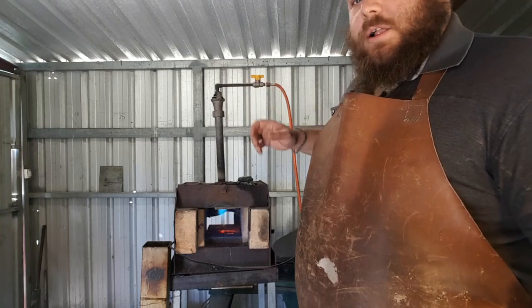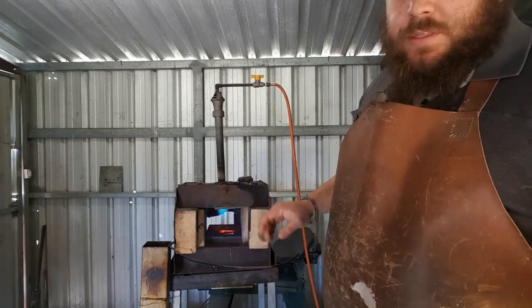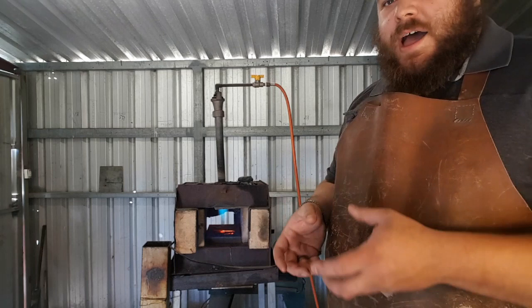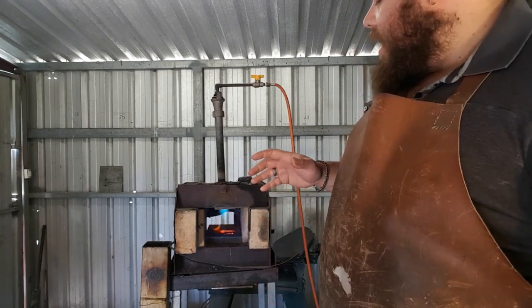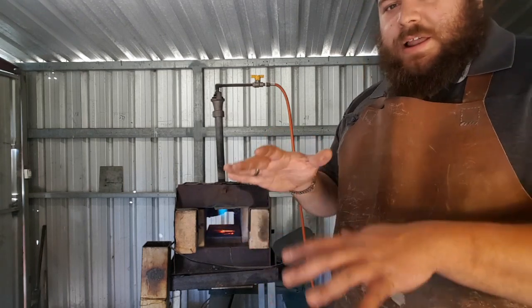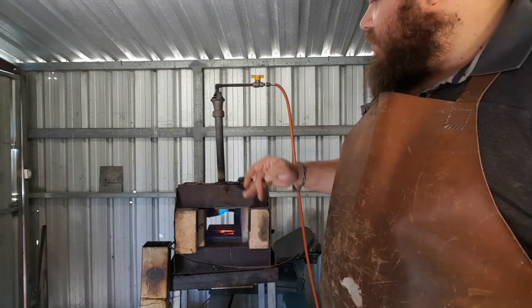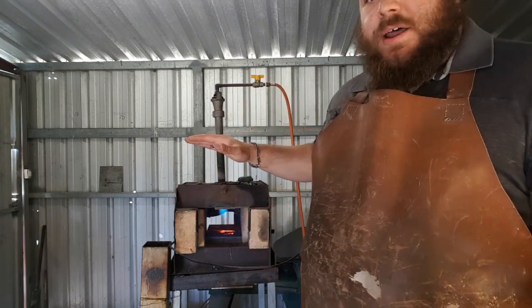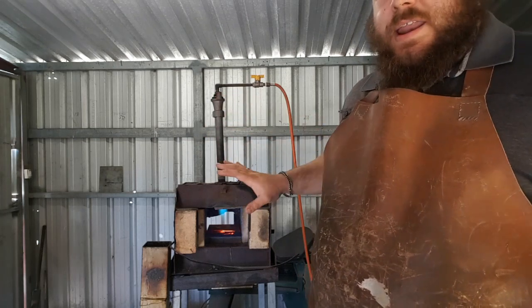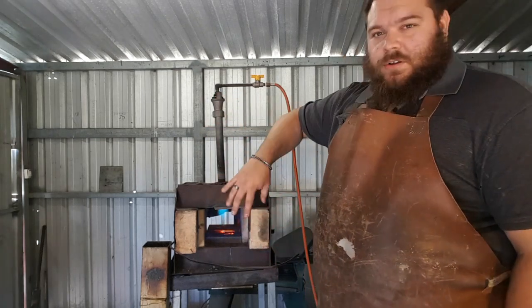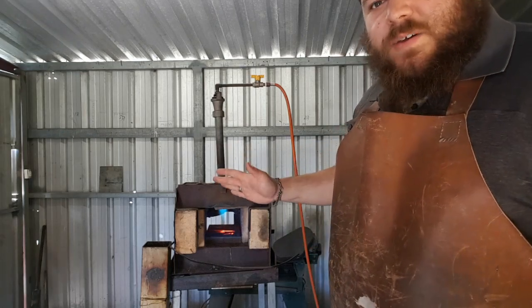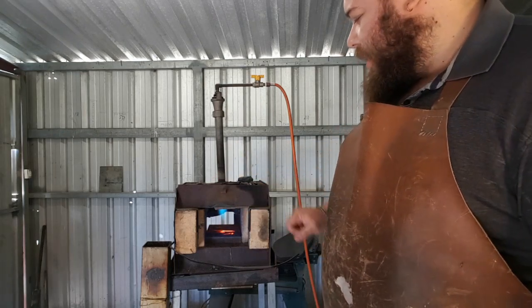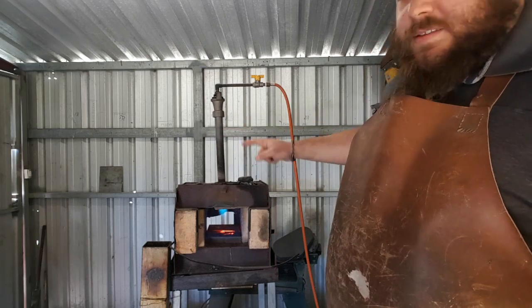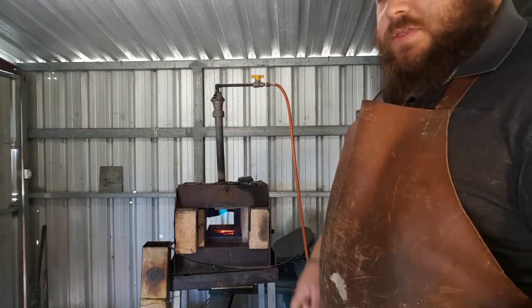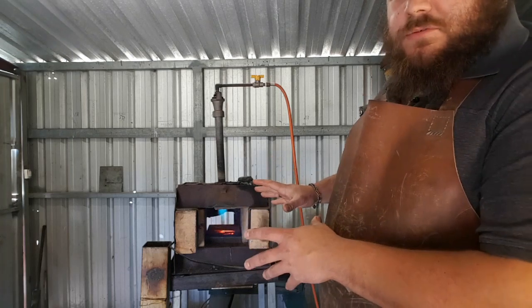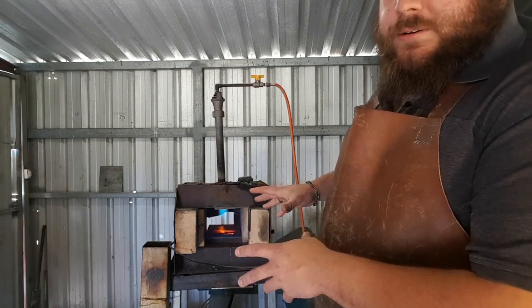At the low air, you will get what's called luffing, which is what happened with that forge just then. It's when the flame can't keep a solid stream. You don't want that to happen too much because that will really fluctuate your temperature. So try and get it to the point where the air is just low enough that you can still maintain a steady stream, but you're getting these nice tendrils of fire coming out. It's not very obvious on the video, but there are flames coming out to the top of the forge right now. So this is the temperature we want the forge to run at when we're starting to do heat treating.